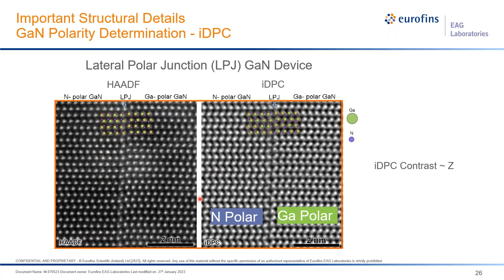Another application of high resolution is looking at AlN polarity control. Starting with sapphire and growing AlN, AC STEM can directly image both the aluminum and nitrogen columns—we can see it starts as nitrogen-polar material, and then introducing some oxygen causes flipping of the polarity, which we can directly see in the HAADF image. For GaN, HAADF imaging is less successful at understanding polarity. This is an example of a lateral polar junction device in GaN with an inversion domain boundary. HAADF can only clearly see the gallium columns due to Z-squared sensitivity—there's too big a difference between gallium and nitrogen.